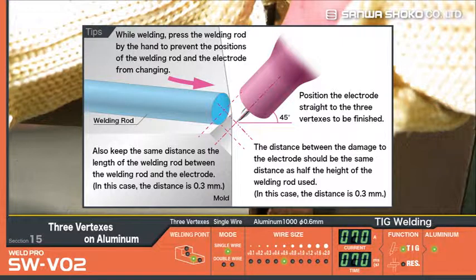Position the electrode straight to the 3 vertices to be finished. The distance between the damage and the electrode should be the same as half the height of the welding rod used. In this case, the distance is 0.3 millimeters. Also, keep the same distance as the length of the welding rod between the welding rod and the electrode. While welding, press the welding rod by hand to prevent the position of the welding rod and the electrode from changing.